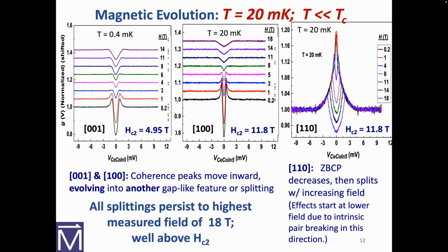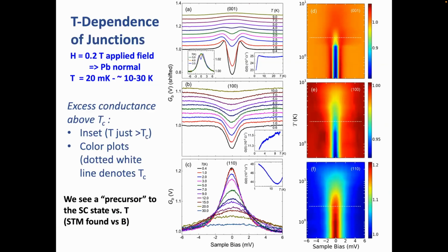What we're seeing is that we're killing the superconducting gap as we expect, and then this other kind of splitting, this V-shaped thing, grows linearly with magnetic field. We see the exact same thing in the A-axis direction. There, HC2 is about 12 Tesla, and we see at 11, 14, 18 Tesla that something's growing, and we can't explain it. It's not superconductivity. That's the only thing we all know, because we're at low temperature but well above HC2.